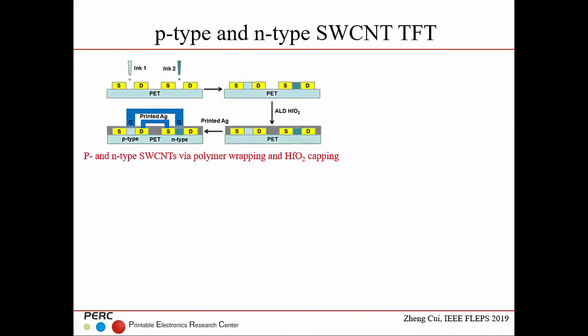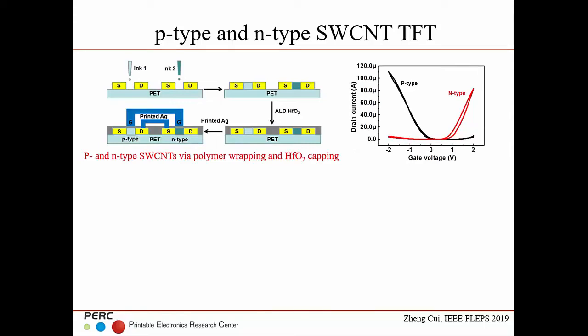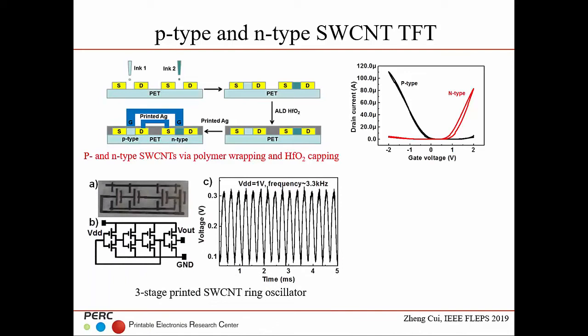So we have three different ways to turn normally P-type semiconductor transistors into N-type. The first scheme is that we use a different polymer to wrap up the carbon nanotube, so that when they are printed and covered with oxide, the different inks appear to be of different type. It can be P-type and N-type. In this way, we have made P-type and N-type from different inks. You can see from the characteristics that they are truly different polarity transistors. So that's the three-stage printed ring oscillator using both P-type and N-type, and it gets quite good performance.